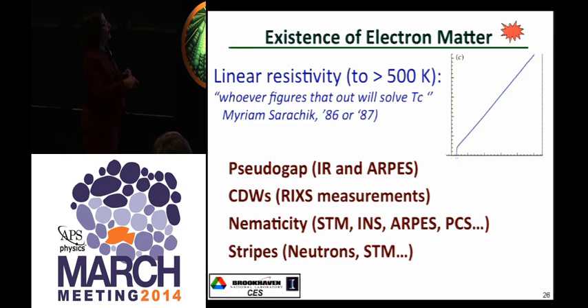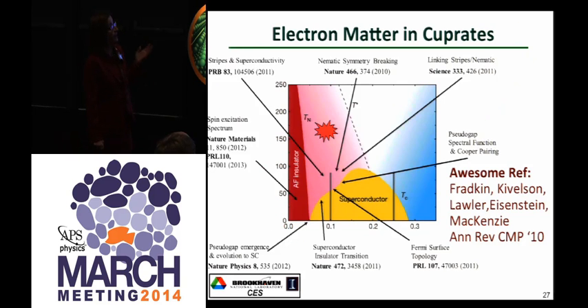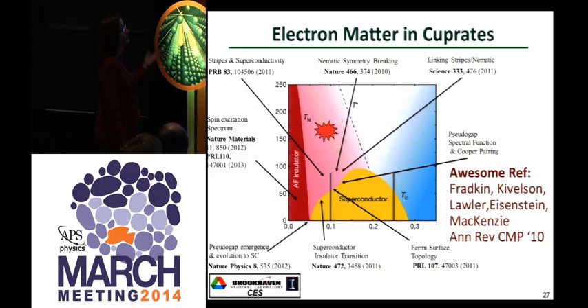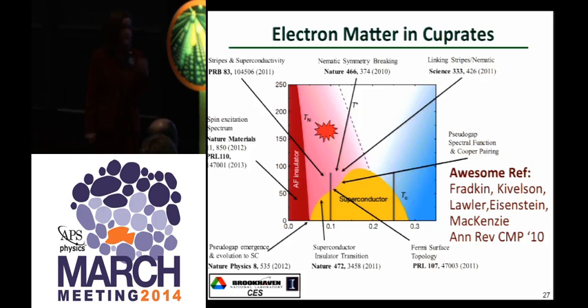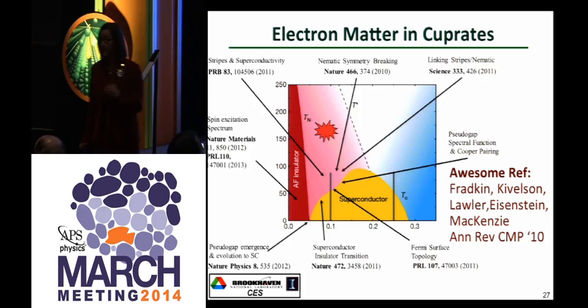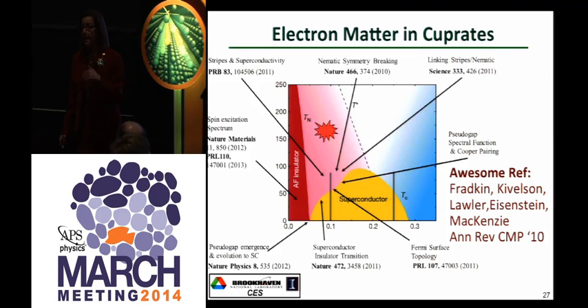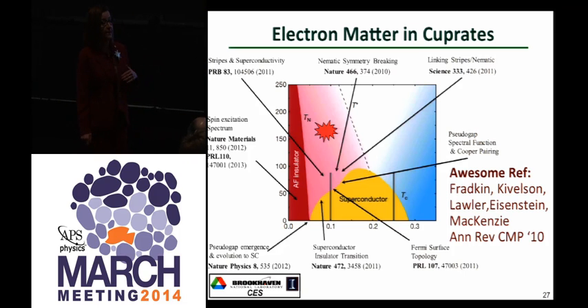Some of the other things I'm going to point out are the pseudogap that we see in the cuprates, the charge density waves in the cuprates, and the nematicity, which I will mention in the iron-based superconductors. So here's a figure that points out just a very, very small snapshot of some of the electron matter that's been measured. Yes, it's a little myopic to the people I know, and I apologize. But there is a huge amount in the literature that tells us a great deal. And if anybody wants to read this reference here, with two of our speakers here, I recommend that, and it'll give you a really good overview in defining electronic nematicity and stripes and the origin of these things.